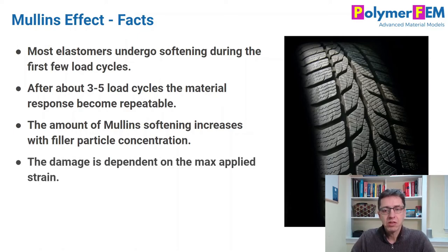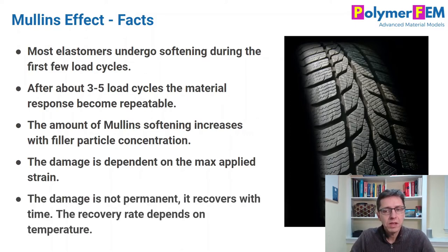What's interesting is how it manifests itself in the stress-strain response. It's dependent predominantly on the max strain or max energy that the material has been exposed to. But note that the Mullins effect is not permanent. This damage recovers over time. If you give the material a chance to recover, the Mullins damage will go away, and this recovery is relatively slow for some materials but can be made faster in an elevated temperature environment.